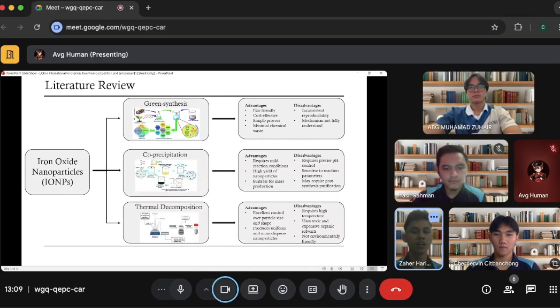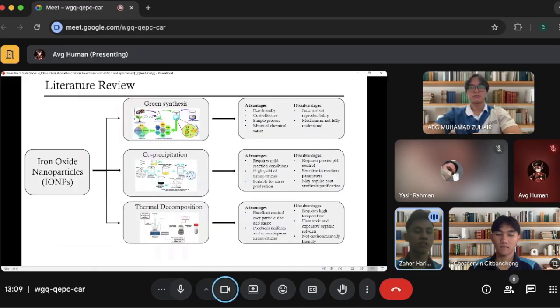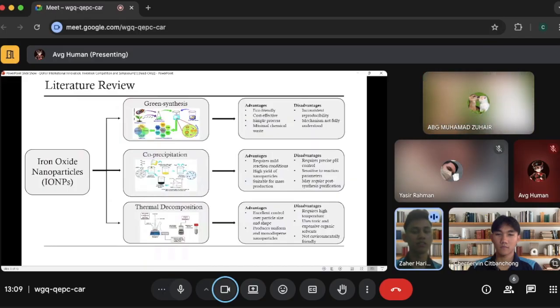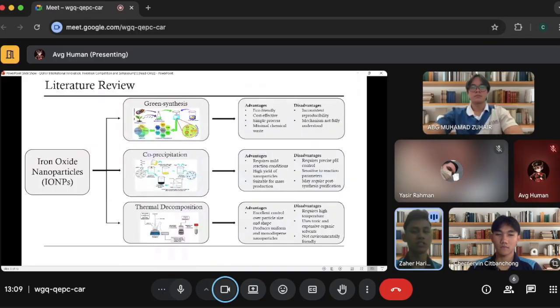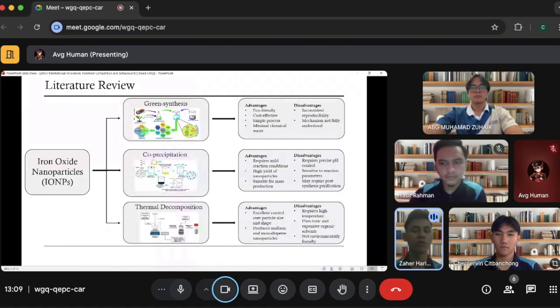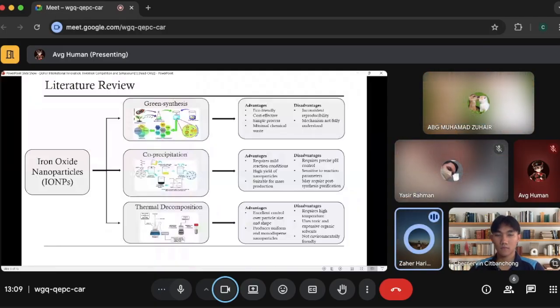There are several methods to synthesize iron oxide nanoparticles: green synthesis, co-precipitation, and thermal decomposition. We chose green synthesis because it operates under mild conditions, it reduces chemical waste, and it uses plant-based material like lemongrass extract as both reducing and capping agent. This makes it an eco-friendly, low-toxicity, and sustainable method, which aligns well with our adsorption process for water treatment. By combining adsorption and green synthesized iron oxide nanoparticles, we achieve a solution that is both effective and environmentally friendly.